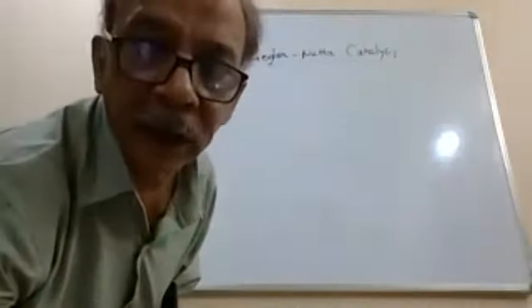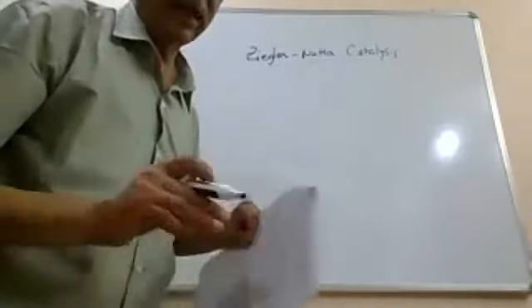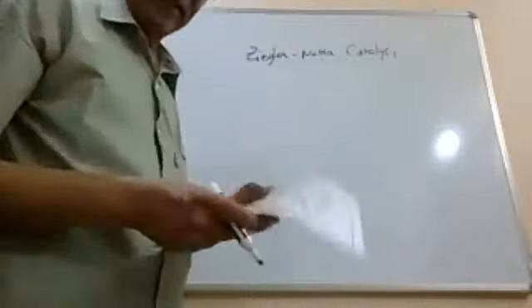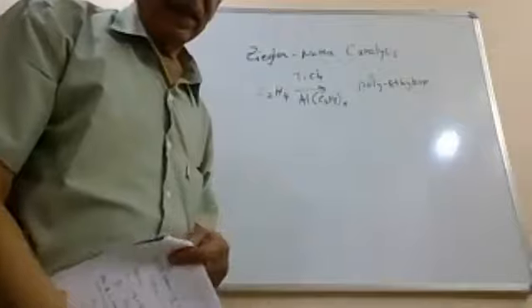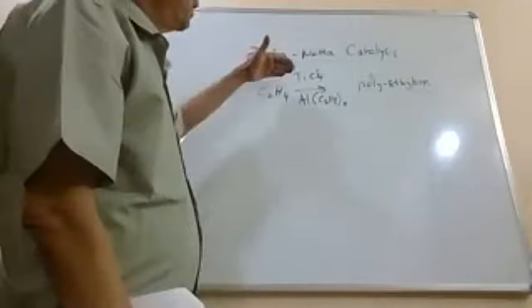So let me go to the board. So this is the Ziegler-Natta catalysis. What I read in the literature is that this is an accidental discovery. It was not intended for this, but somehow they just stumbled upon it by accident. So the catalyst here is, if you have ethylene and you pass ethylene onto titanium chloride, TiCl4, the titanium 4 chloride, in the presence of triethyl aluminum, you get polyethylene.